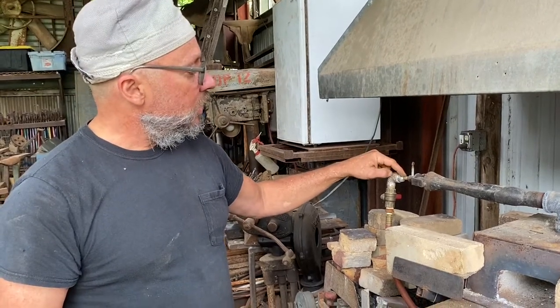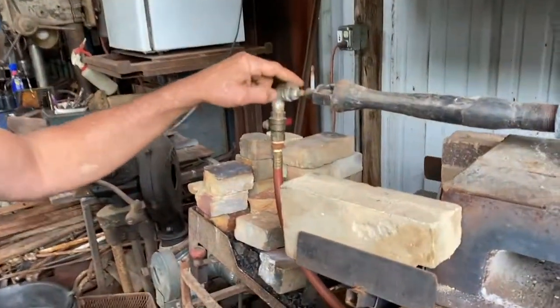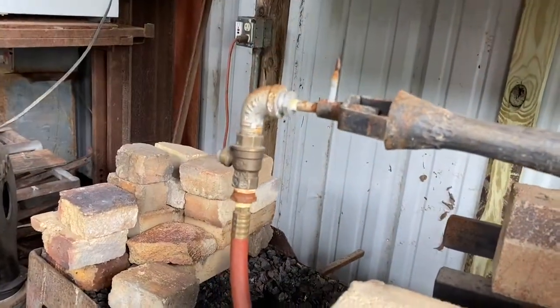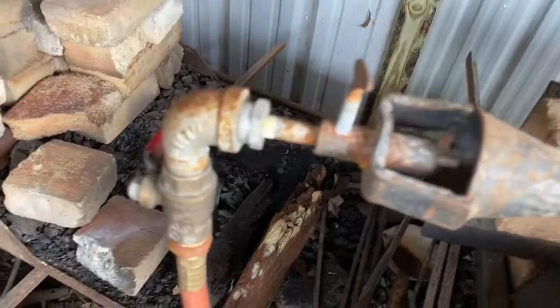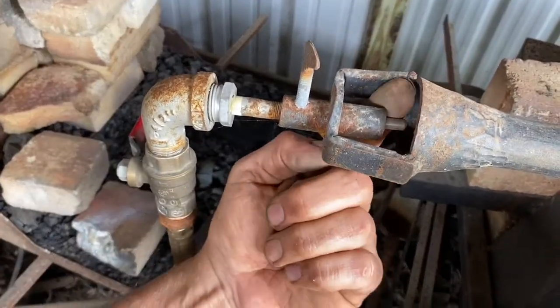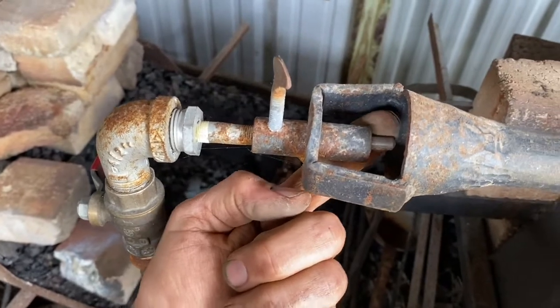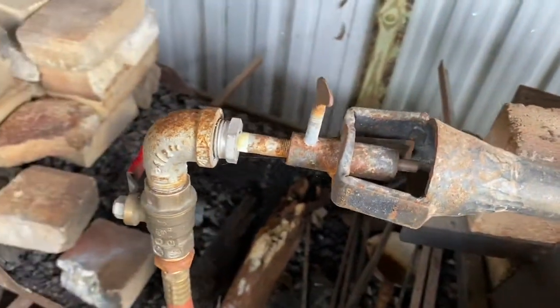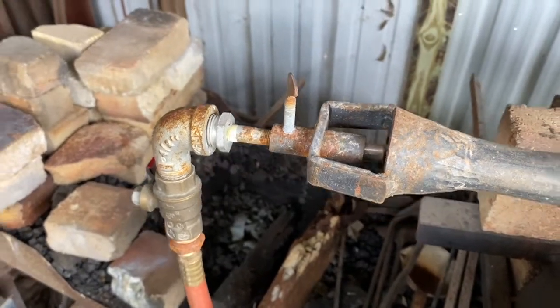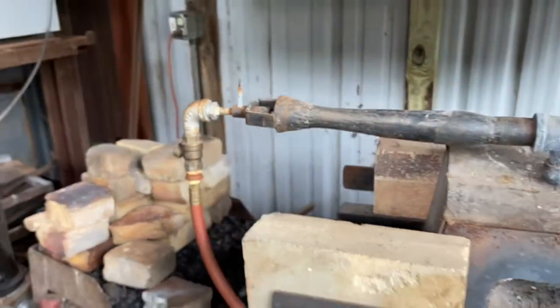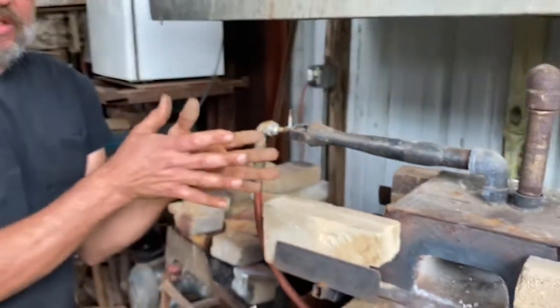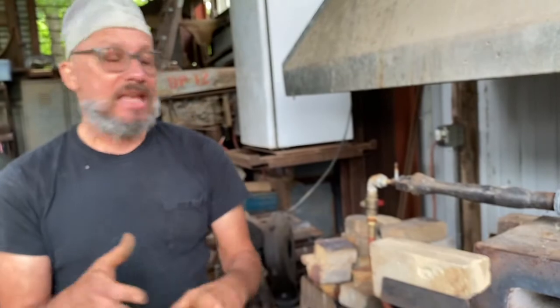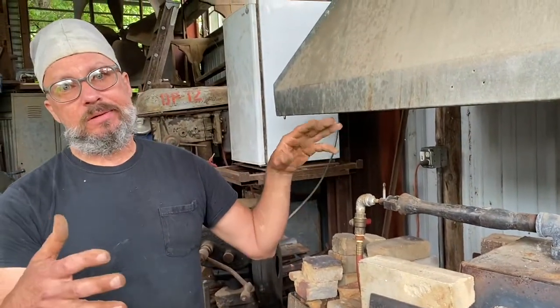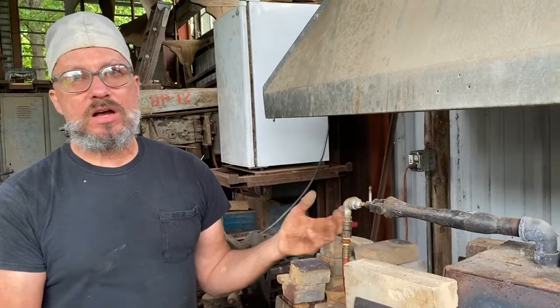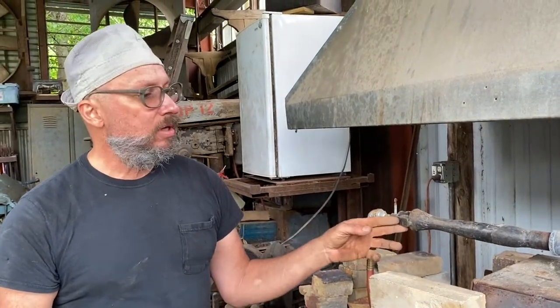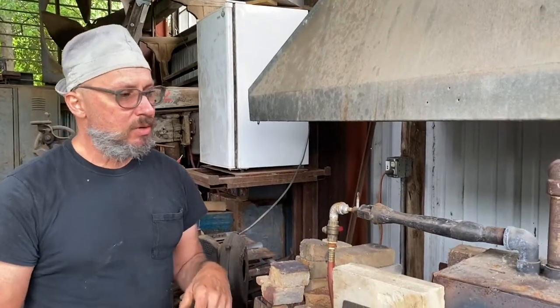So if you can neck down to 1/8 inch IPS, then you can put a MIG tip on that, and you can change the MIG tips out. It's pretty interesting because even though it's a 30 thousandths MIG tip, so there's my MIG tip, if you put a tip cleaner in that, sometimes they'll be loose, sometimes they'll be tight. It's nominally 30 thousandths, but that's an advantage because you can line them up to where the tip cleaner was the tightest and the loosest, and you can jet your forge that way. If you're at elevation, you're going to want to lean it out because there's not enough oxygen. If you're at sea level, then you can rich it because you've got more oxygen. So it's just another way of tuning your forge.